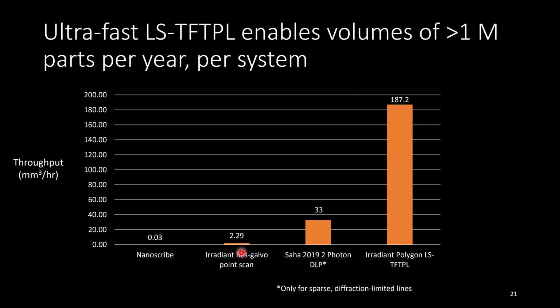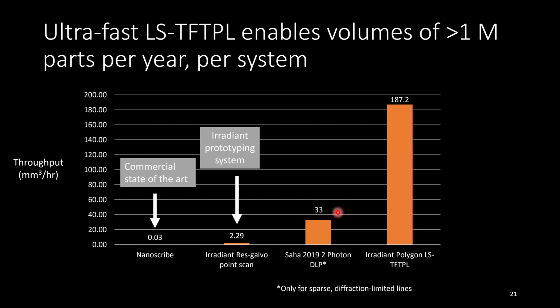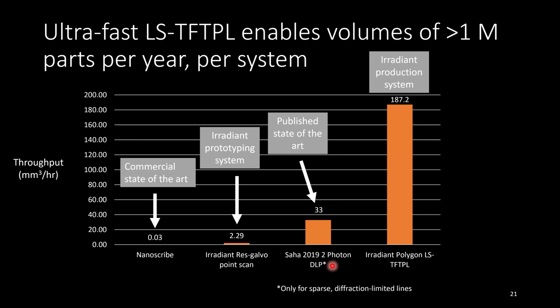And then this 2019 two-photon DLP paper, they demonstrated a throughput of about 33 cubic millimeters per hour. About 1,000 times faster than this, but of course with the big asterisk that that's only for sparse diffraction limited lines. And then we've demonstrated a production system that goes up to close to 200 cubic millimeters per hour. So now about 10,000 times faster than these point scan systems.